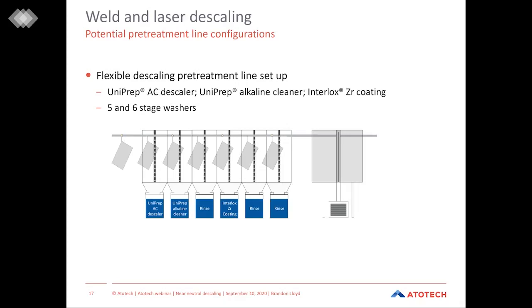So you can see in stage 1, we have implemented the Uniprep AC descaler. Then we move immediately to the Uniprep alkaline cleaner. Because of the pH of the descalers, going immediately to the alkaline cleaner will not have much of an impact on the process control because it is operating at relatively near neutral pH. Then we move to a rinse before the Interlox Zr coating, additional rinses, and then again to the dry off and paint application.